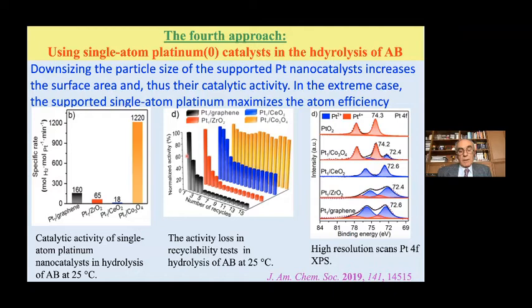The activity of single atom platinum on graphene decreases very quickly. The same for zirconia and also for ceria, which decreases rapidly at first. However, in the case of single atom platinum on cobalt oxide, the activity remains, I should say, more or less within 10% variation. This is attributed to the metal support interaction, which is confirmed by the binding energy of platinum in the XPS. Only cobalt oxide supported single atom platinum has very high binding energy, as high as platinum 4, while the others have lower binding energy.